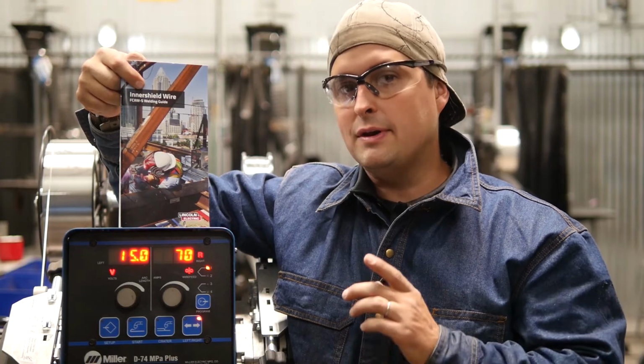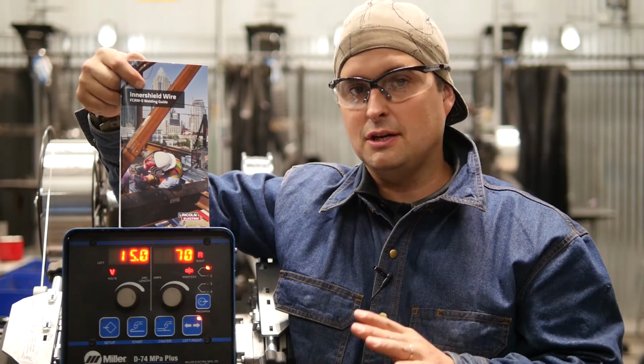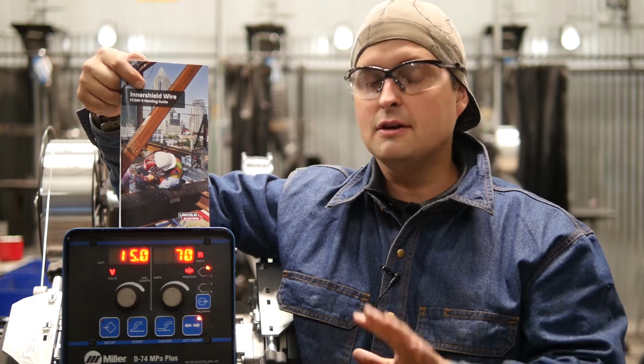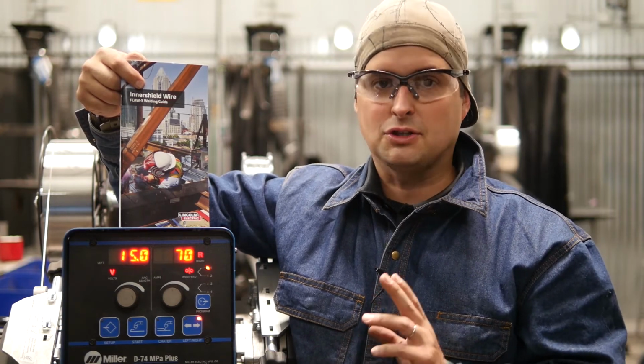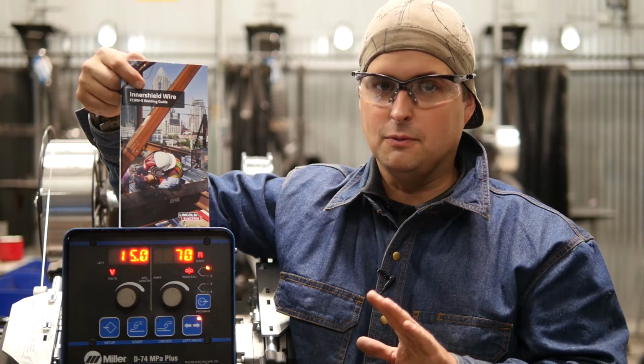Now, one thing to note here, self-shielded FluxCore wire, like the kind we're using in our 211, runs on DC electrode negative. So if you typically use your machine for MIG, which will be set up positive, you'll want to change that before you start to weld with this wire, or you won't get any good results at all.